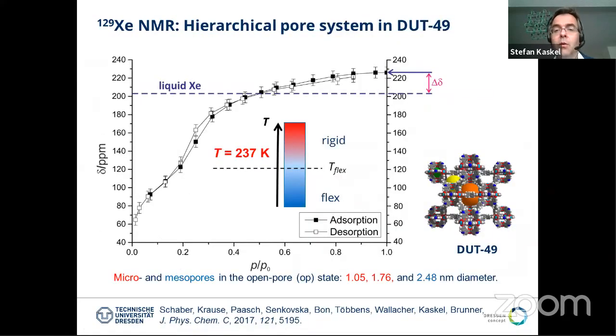And I will show this now also for our DUT-49, which is the flexible material. And here I show a case where there is no structural change, because the structural change is also temperature dependent. Above a critical temperature, which I've just mentioned as T flex in this slide, at warm temperature, basically there is no structural transformation with xenon. And we see a similar type 1 or type 1b adsorption isotherm. Here again, this is the chemical shift, because the xenon is so fast traveling in between the pores that we cannot distinguish if it is in the large pore or in the small pore.